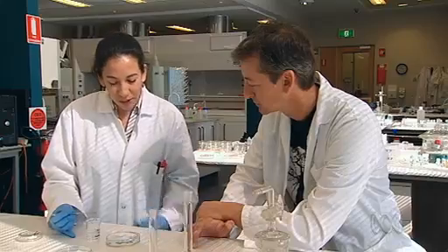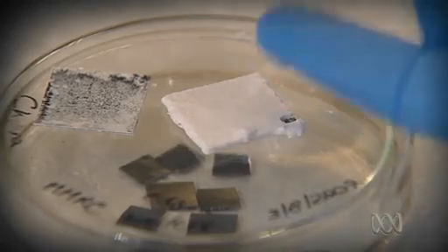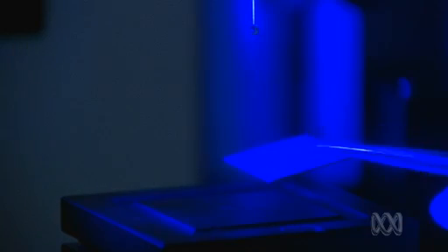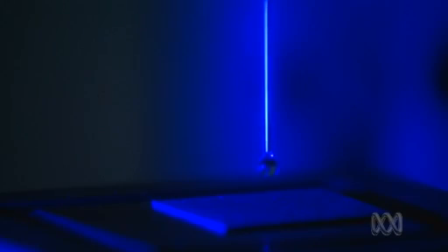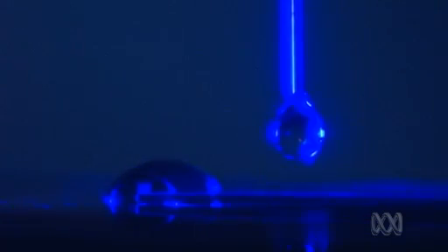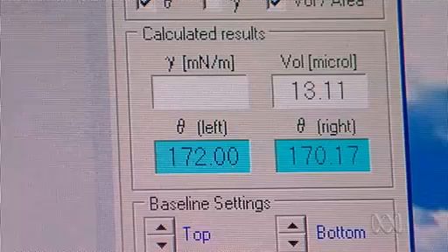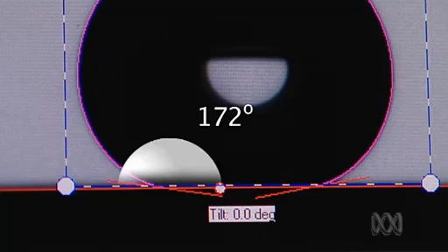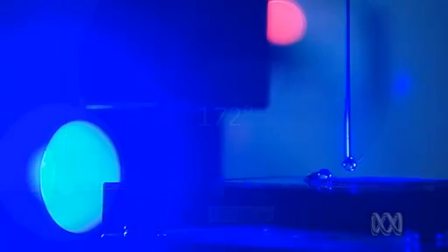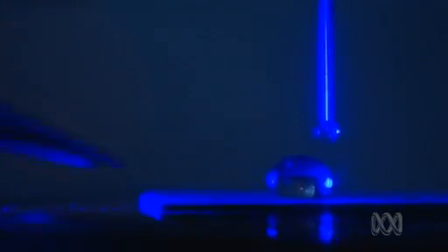So if I do this many times, I end up with something that looks like this, that has a very high contact angle. A high contact angle means the surface is water repellent. On this surface, water can form a near perfect sphere and roll straight off. With a contact angle of 172 degrees, it's as water repellent as a lotus leaf.